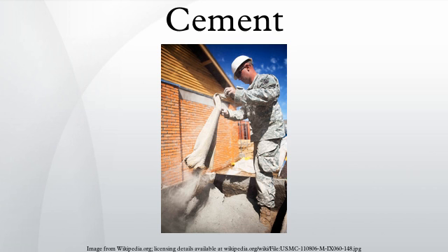Portland cement blends. Portland cement blends are often available as interground mixtures from cement producers, but similar formulations are often also mixed from the ground components at the concrete mixing plant. Portland blast furnace cement contains up to 70% ground granulated blast furnace slag, with the rest Portland clinker and a little gypsum. All compositions produce high ultimate strength, but as slag content is increased, early strength is reduced, while sulfate resistance increases and heat evolution diminishes. Used as an economic alternative to Portland sulfate-resisting and low-heat cements.